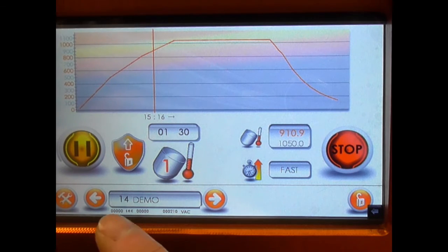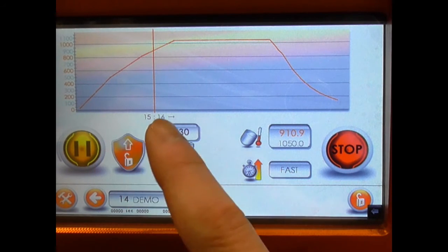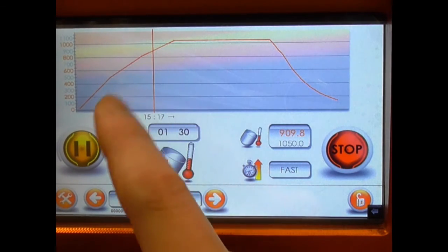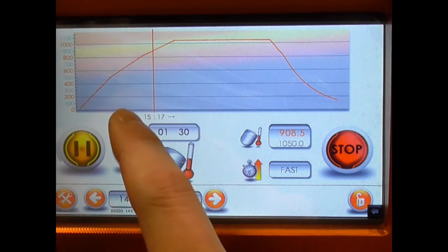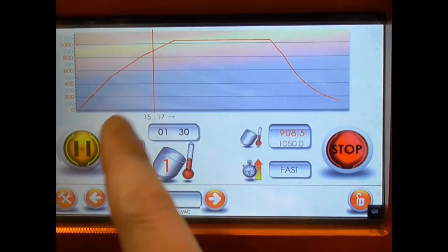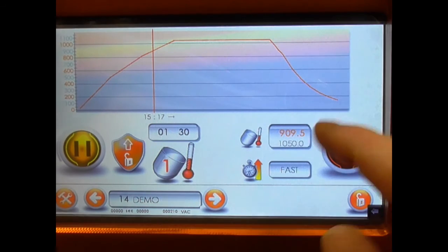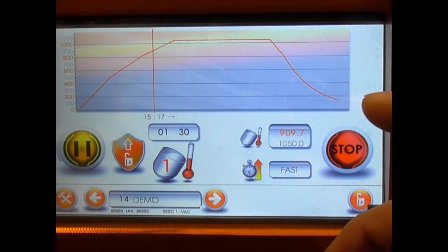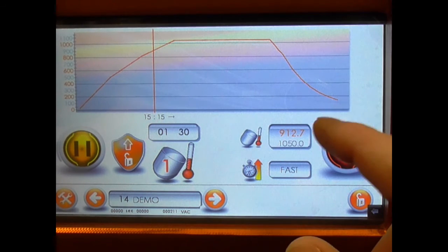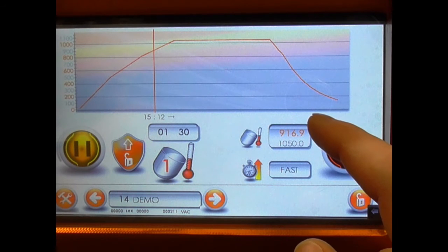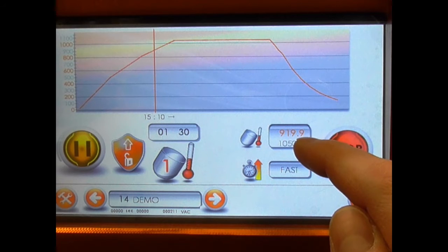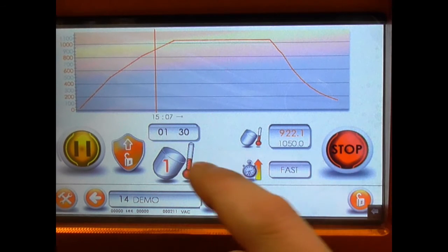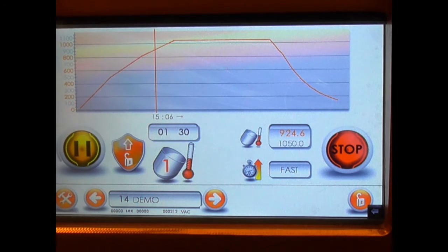We will be able to follow the status of the method by following the vertical red bar on the display, which will show you how much time remains and where you are at the different steps. Of course, we introduced the cool crucible holder inside the furnace. It dropped the temperature a little bit. The red value you can read here will slowly come back to target temperature at the bottom here, and that is where the first step will start.